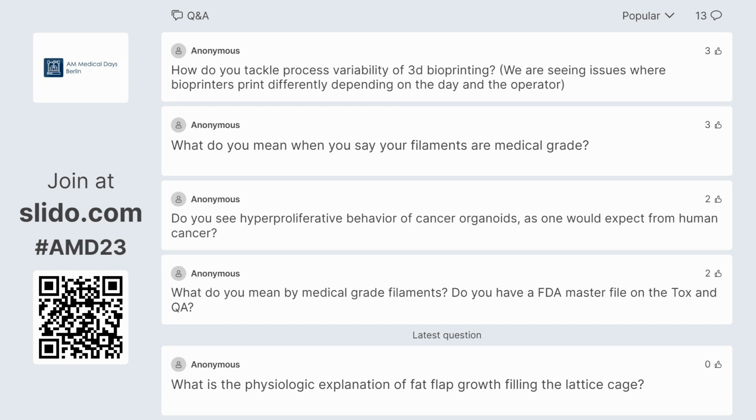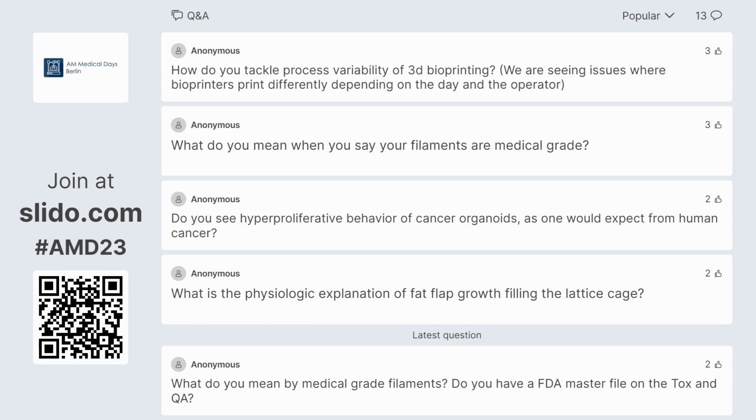So yeah, this is one of the questions we assess starting the clinical trials. And it's softer at 37 degrees. The Tg of the material is softer at the body temperature. And based on the pain scale of the patient, she comes back the first month, 3 months, 6 months on the protocol. So they did not feel really hard and tough. And thanks to the resorption, after 4 to 6 months, it gets really, really softer, and the patient doesn't feel it after 6 months. It's hard outside the body, but soft inside.